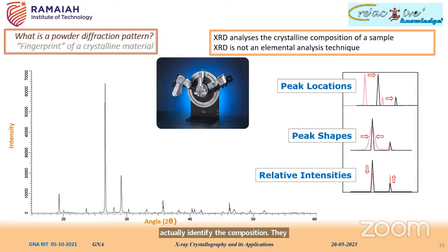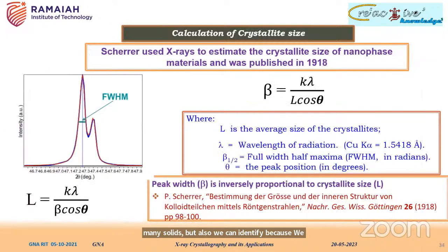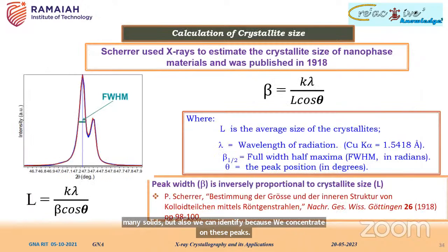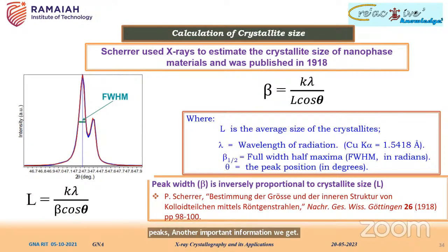If we have a mixture of many solids, that also we can identify, because we concentrate on the peak positions, shapes, and intensities. Another important piece of information we get is that we can use the Scherrer formula to know the crystallite size. Crystallite size is not particle size. The average size of the small crystalline domains present in the sample can be quickly calculated using this data by measuring the full width of the peak. Suppose this is a high intensity peak in the powder XRD pattern.